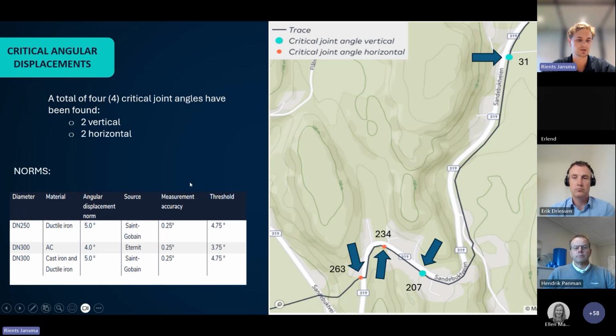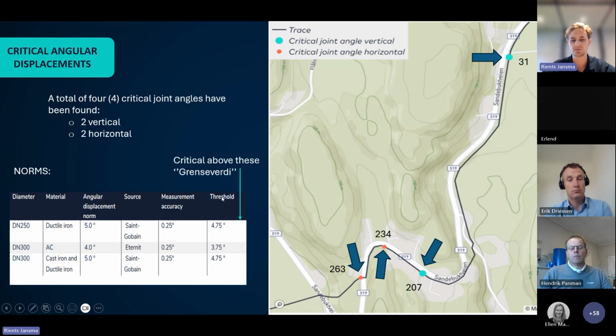So at the down left, you can see a table of the norms. So at the left side, the diameters, 250, 300, 300, the materials, ductile iron, asbestos cement, cast iron, and ductile iron. And there's always a norm for this. So at ductile iron, cast iron, it's 5 degrees. At the asbestos cement, it's 4 degrees. And our measurement accuracy is 0.25. So we build in a threshold, or a grensverdi in Norwegian, to account these as critical.